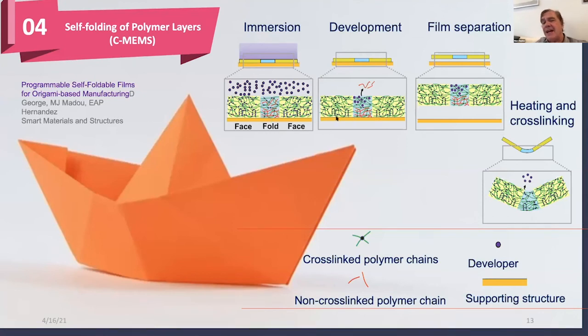And if I have this locked onto a surface, I basically have a bilayer. And when I do heating of this film and cross-linking, I make this nice bend in the structure, and the bend will depend on the escaping solvent in the fold region. So here, differently from using the droplet, we are using the forces that occur when, by heating, you have the solvent evaporating out of the polymer material.